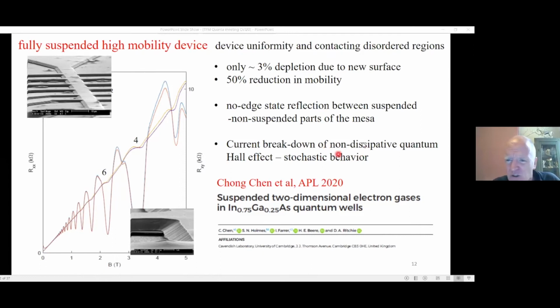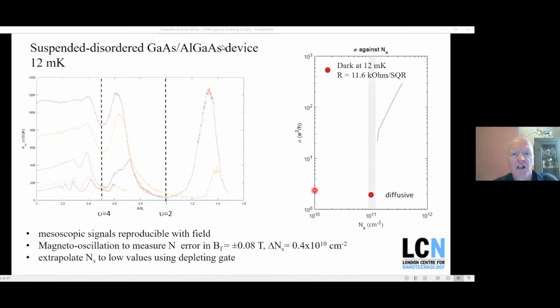We studied non-dissipative breakdown of the quantum Hall effect. It's kind of a stochastic behavior, but there's a very, very clear difference. This is an SEM image here. This is the 500 nanometer InGaAs layer, which is etched away. When you remove that, there's a clear difference between an isolated and a thermally contacted device. It was published in APL this year.